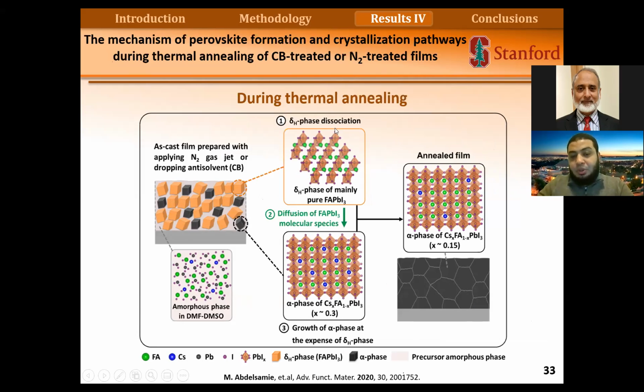And when we tune this, what we found about the mechanism is that the delta phase dissociates as we apply annealing, and the delta phase we found is mainly pure FA. But the alpha phase we found has a different composition than the final state. In the final state, the cesium is 15% and FA 85%. But when we watched the film formation, we found that initially the crystalline perovskite phase had a different composition, having 30% cesium. So we have a segregation. The cesium goes into the alpha phase, and FA goes into the delta phase.